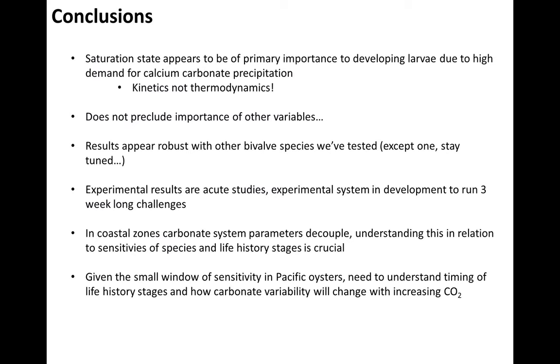So just to wrap up here, saturation state appears to be of primary importance to developing larvae due to this high demand for calcium carbonate precipitation, and we're arguing that it's the kinetics, not the thermodynamics, that are important. So it's the rate at which the organism needs to build that shell versus how easy it is to build that shell. And this doesn't preclude the importance of other variables, and we know from lots of great studies other people have done that some of these organisms lack the ability to regulate internal pH very well, and so these are certainly going to come into play and create stressors on these organisms.